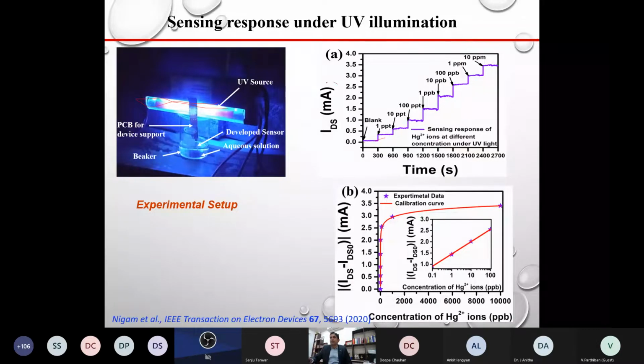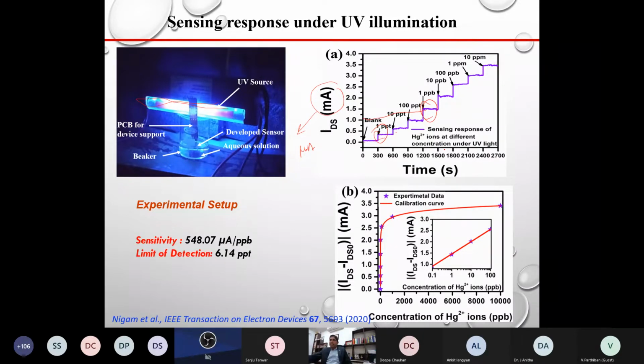Here you can see our current is in the milliampere. If you remember, in the previous case without the UV source, the current was in microampere. Because the current is very high, we can easily detect it, and we can even detect 1 ppt also. That was not possible in the previous case, and as per the WHO-defined limit of around 1 ppb, a change at 1 ppb we can easily detect. Here the sensitivity is around 548 microampere per ppb, which is very high compared to without the UV source.